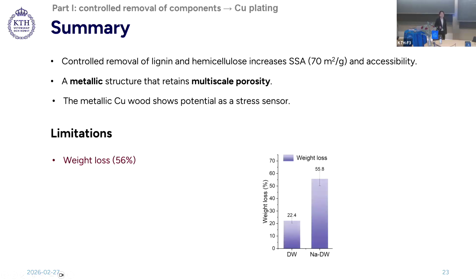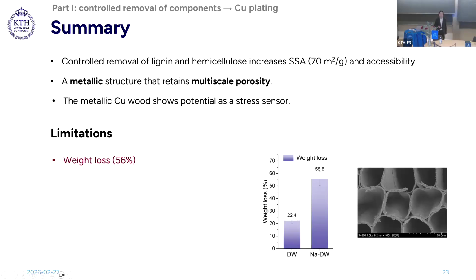Despite the promise, this approach has certain limitations. From material economy point of view, the significant weight loss is a drawback. Moreover, this cell engineering approach focuses on creating porosity within the cell wall. However, the lumen space, which accounts for more than 50% in most wood species, remains underutilized. Leveraging the lumen space will further increase the structural potential of wood templates.